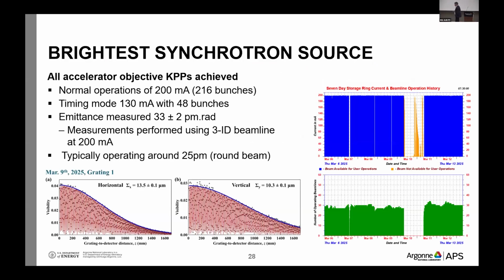By the time we had achieved 200 milliamp, which is the nominal current that this new machine is running at, it's twice the current of the old machine, of course, because brightness is important, but also because, as you know, the energy of the machine has shifted down from 7 GeV to 6 GeV, so this is to ensure high brightness also at high photon energy.